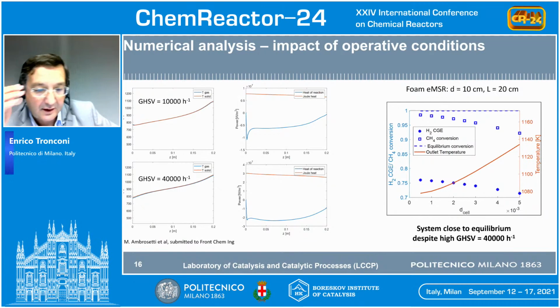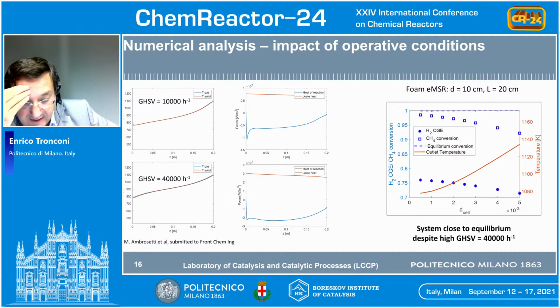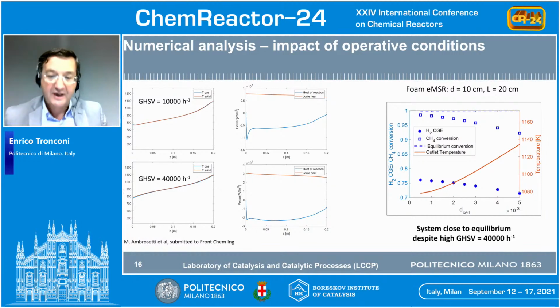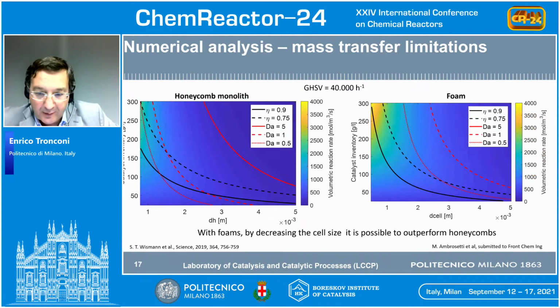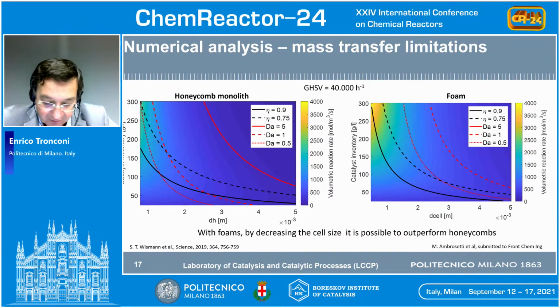We predict only very small differences between the gas and the solid temperature and concentrations, and also limited deviations from the equilibrium conversion. And this result is basically due to the very high activity of the catalyst, but most of all to the enhanced heat and mass transport properties of the foams that we are adopting. We have also run some comparative simulations assuming both honeycomb monoliths and foams. I will not go into the details of these results for the interest of time, but I will just mention that in general, in the case of the honeycomb, both internal heat and internal mass transfer limitations are more severe than in the case of foams.